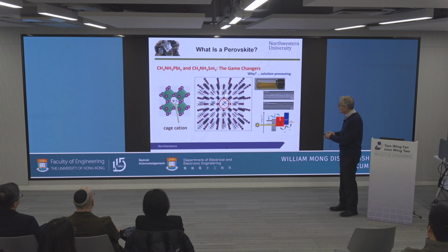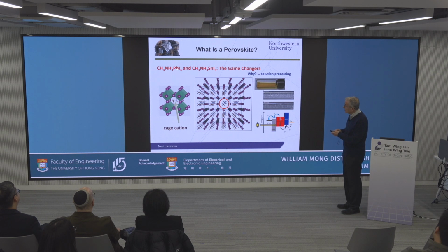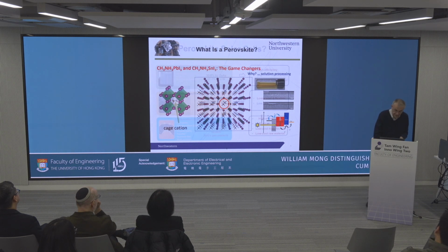And if the structure is negative, for example, in these formulas, lead is 2+, iodine is -1, so the whole thing is -1, so it requires charge balance, and so a small molecule can fit in the cage and balance the structure. The most important perovskites are these two, the lead and the tin-based. Okay, so that's one.